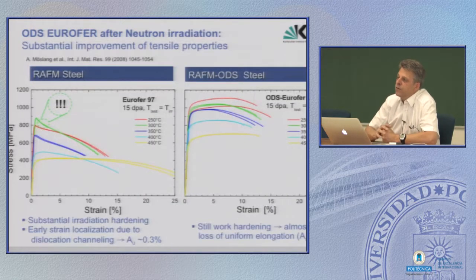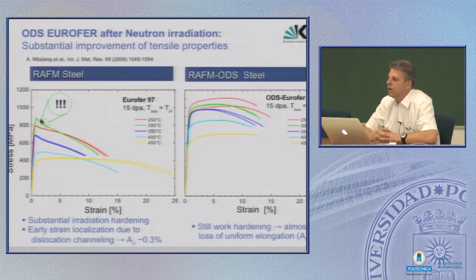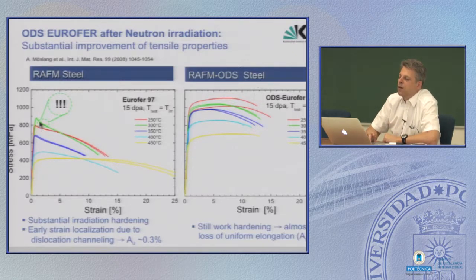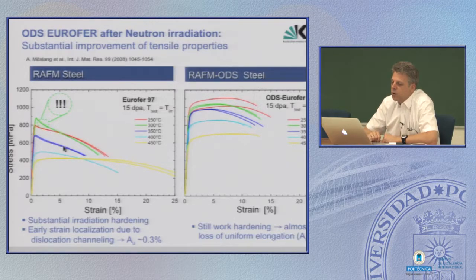Another beneficial thing of these ODS steels is, what we have seen, the loss of strain hardening, that the usual 9% chromium steels after some irradiation time, they embrittle, they get harder, they suffer from irradiation hardening, that's one point, but they lose their cold working part, their plastic stability over a broad range of strain. If you would load them above this limit, then we would have a plastic collapse of all components you would build with this material. Of course, you can restrict the stresses to certain limits, and this will not happen. But still, this is not exactly the way you want your material to look like after irradiation.